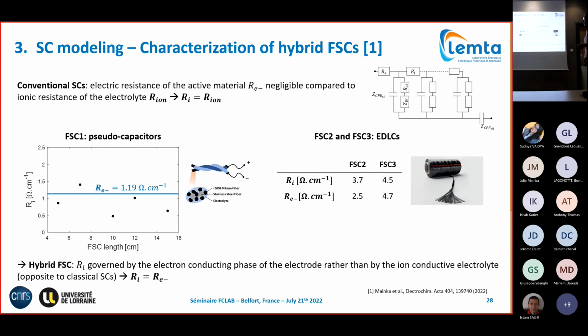And we compare this value identified from the fitting curves with the electrical resistance of the active material, the mixture of reduced graphene oxide and another component, that our colleagues measured independently by potentiostatic measurements. And if you see, we are very close to the electric resistance, the resistance linked to electron conduction inside the material, rather than to the electrolyte resistance. So for these fiber-shaped pseudo-capacitive supercapacitors, this internal resistance seems to be linked rather to electron conduction than to ion conduction.